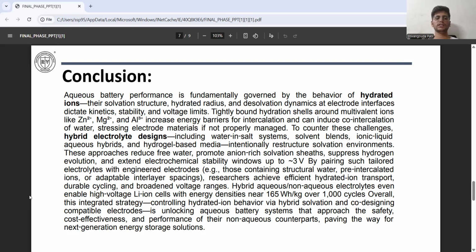To counter these challenges, hybrid electrolyte designs, including water in salt systems, solvent blends, ionic liquid aqueous hybrids, and hydrogel based media, intentionally restructure solvent environments. These approaches reduce free water, promote anion-rich solvation sheaths, suppress hydrogen evolution, and extend electrochemical stability windows up to 3V by pairing such tailored electrolytes with engineered electrodes.